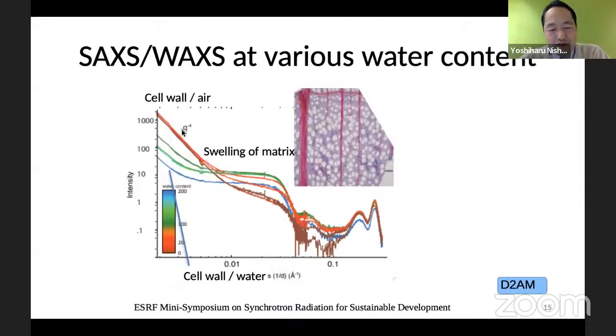So what we see here is, in the first place, we prepare a wood sample where all the pores are filled with water, or a completely dried wood piece, which is in this brown. In this very small Q region, what we see is the interface at the pore, actually. So if this is filled with air, the contrast between air and the cell wall is high. So we have a strong surface scattering, whereas when it's filled with water, this part, we have relatively low scattering intensity because of smaller contrast.